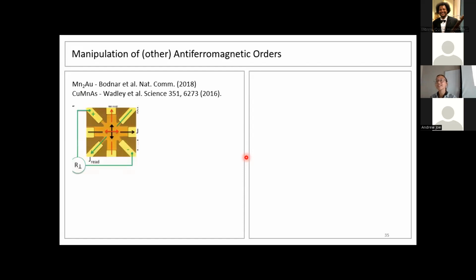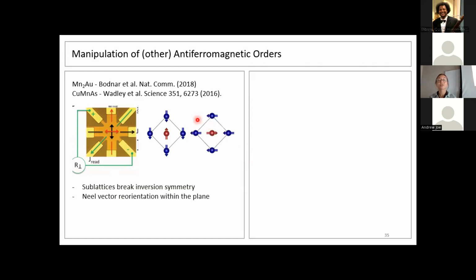So they have a switching device like the one that I showed you, and what they thought was that they were changing the directions of their spins by 90 degrees. So this is exactly the Néel vector rotating by 90 degrees within the plane of their crystal. There's also some consideration that has to do with the symmetry of their crystal, but that's not too important unless anyone's super interested in it. And this requires current densities on the order of 10^7 amps per centimeter squared.